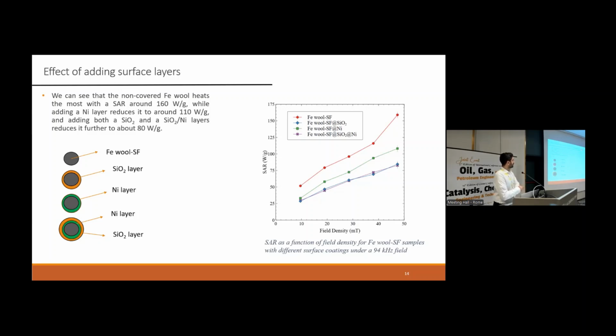And so we studied the naked Fe wool, the regular one, and then one with the silica layer, one with a nickel layer, and one with both nickel and silica layers. And what we observed is that the Fe wool with no layers added had the best heating power, followed by the one with nickel, and lastly, the ones with silica or silica and nickel together.